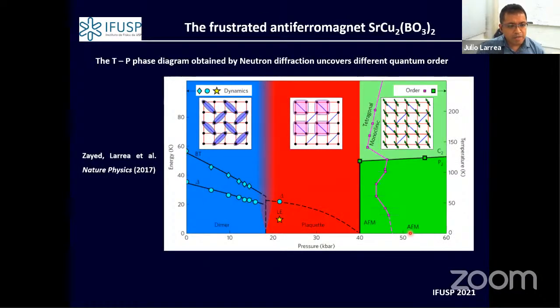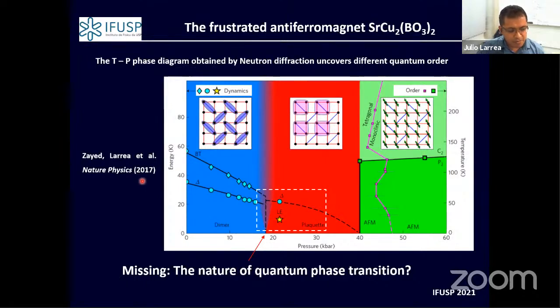So just to summarize, this is the pressure, temperature or energy phase diagram. What you can see is that pressure tunes a decrease of the gap from the singlet to the triplet state. A second energy scale at lower temperature or energy appears, associated with the existence of the plaquette phase, and it is expected that at high pressure this plaquette phase evolves into an antiferromagnetic quantum order. But until this time, we hadn't understood what happens in the phase transition between the dimer and the plaquette phase. So at the time of this publication it was still an open issue to clarify.